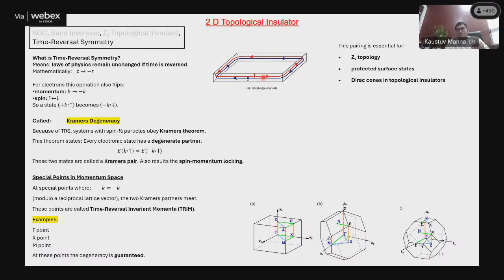So if there is a scattering cross section, let's say the up spin is going forward and it encounters a scattering because of a defect, because of some doping, because of a dislocation, whatever the reason, it doesn't matter. If it is getting scattered, it cannot go inside the material because inside the material is already gapped out. It is insulating. So if there is a scattering, it has to remain on the surface only. The way out is that it can go either backward or forward. If it goes backward after scattering, it adds current to the down channel only. Or if you start with a down channel, then after scattering, it will contribute to the up channel only. Because of the spin momentum locking, you cannot have any other possibilities. As a consequence, these edge states are by default protected.